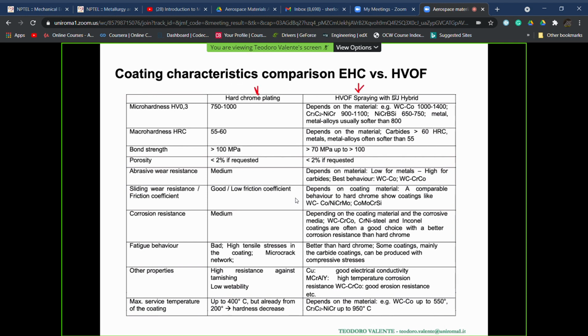This is a typical gun which is based on the use of hydrogen as fuel. And you see here that for the hardness, we can also reach values which are higher than those of the chrome plating. For the macro hardness, we also can have values which are higher than those obtained by hard chrome plating. In terms of porosity, we do not have many differences. In terms of bond strength of the coating with the substrate, we have values which are more or less similar.